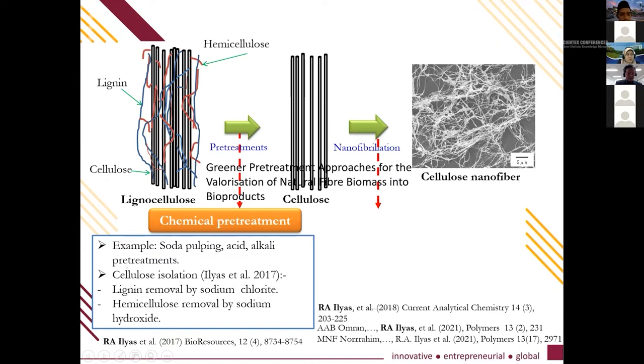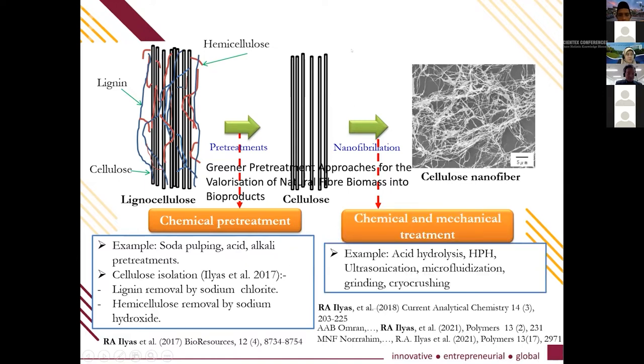In 2017, I isolated cellulose from sugar palm fiber using sodium chlorite to remove the lignin and sodium hydroxide to remove the hemicellulose. After obtaining the cellulose, chemical and mechanical treatments are used to get cellulose nanofibers. Mechanical treatment is typically used to get nanofibrillated cellulose, while chemical treatment — such as acid hydrolysis, high-pressure homogenization, ultrasonication, microfluidization, grinding, and crushing — is used to get nanocrystalline cellulose.